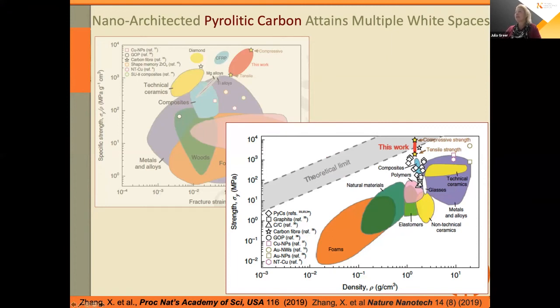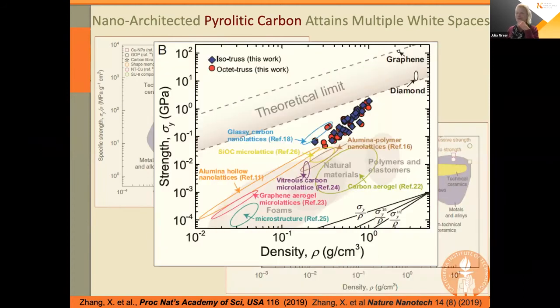I also would like to point out that this notion of theoretical limit has to be rethought and reevaluated when you're dealing with these nanoscale materials. And so this is no longer just the strength of the carbon-carbon bond, but now take into account the graphene, the graphite, and many other carbon-based materials. So we were pleased to see that compared to, say, graphene and diamond, the nanolattices are certainly offering a trajectory to get to these very, very high strengths.